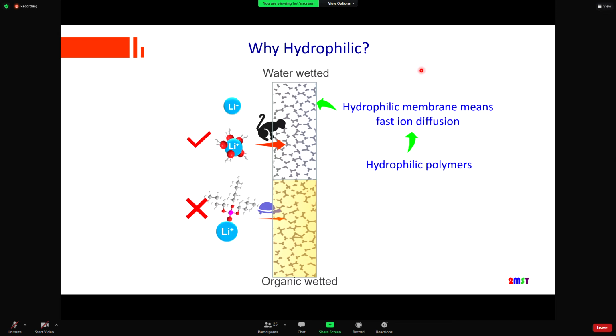Why do we need a hydrophilic membrane? There is a cartoon here that shows for a hydrophilic membrane, the lithium ions diffuse by ions together with some water molecules. But for the organic wetted membrane, because the lithium is conjugated with the extractant, it becomes bulky, so the diffusing coefficient will be low. This is the reason we select the hydrophilic polymer membrane.